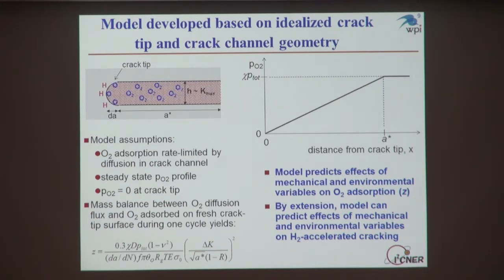So here's the basis of our model, showing you again the profile of this crack. This crack is filled with a hydrogen gas matrix, essentially, and there's some oxygen in that crack. Oxygen is going to adsorb on the crack tip surface and potentially impede hydrogen uptake. And so we're going to assume that this oxygen adsorption is rate limited by diffusion, oxygen diffusion down the crack channel.